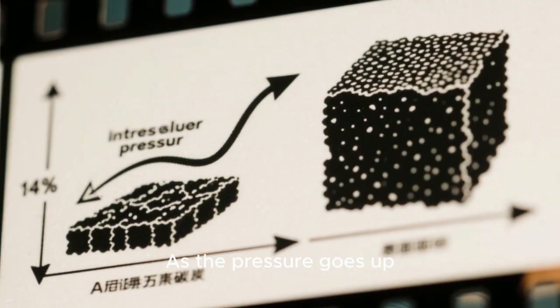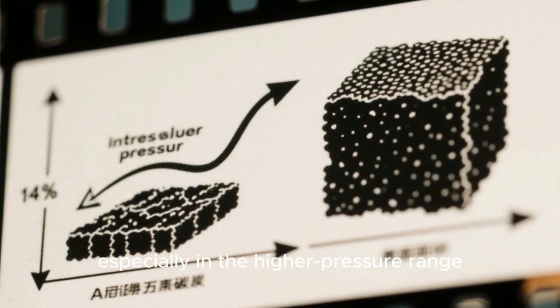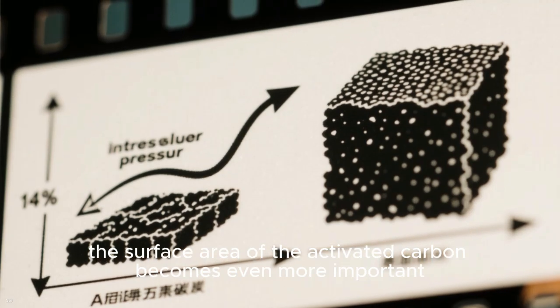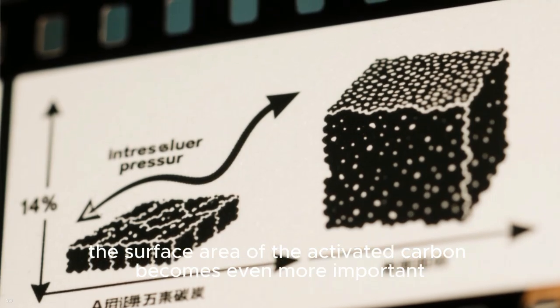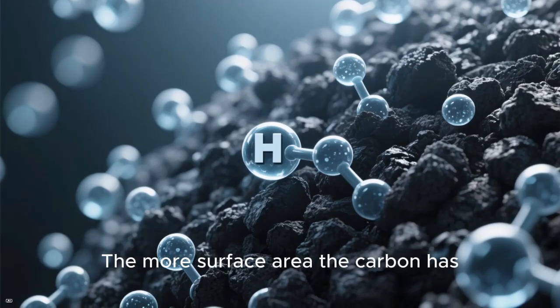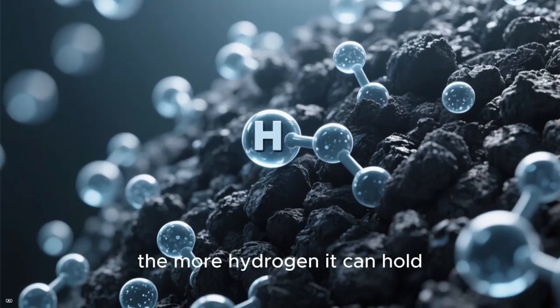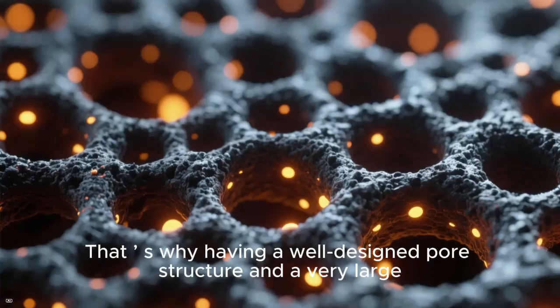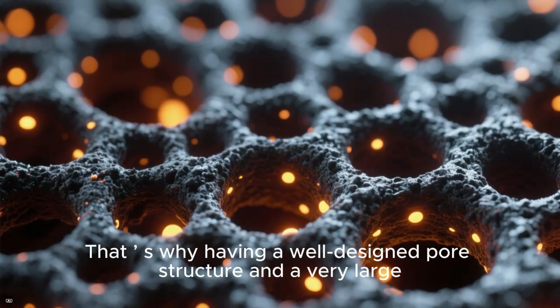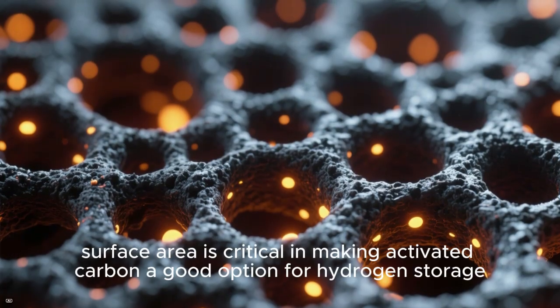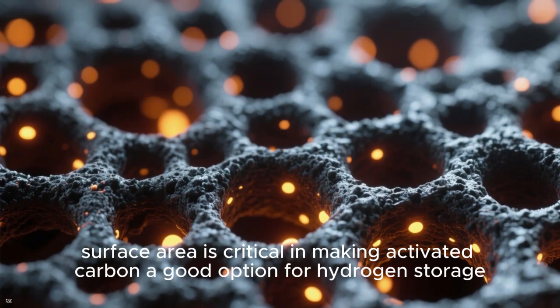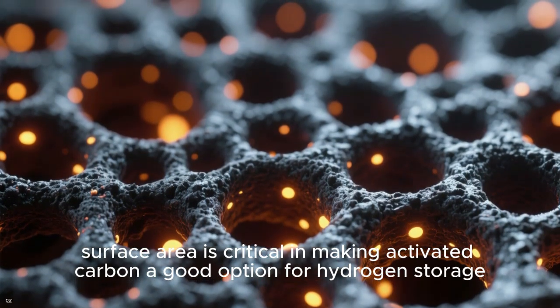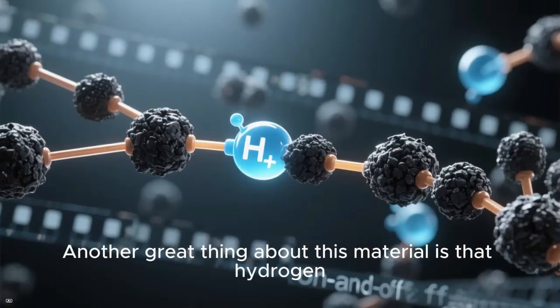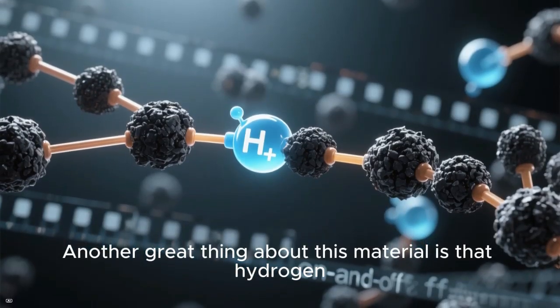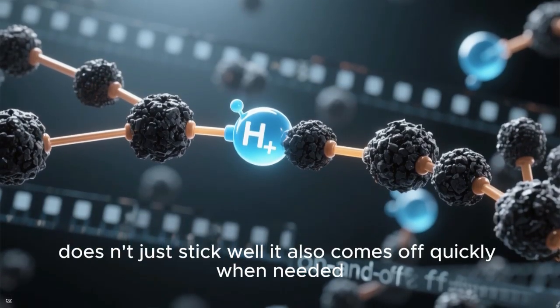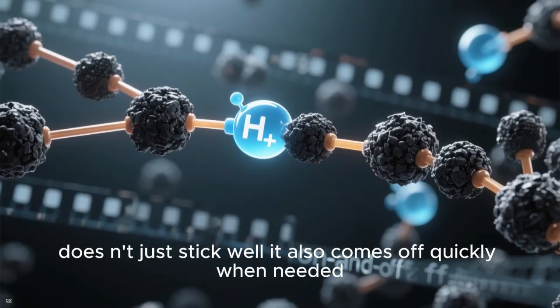As the pressure goes up, especially in the higher pressure range, the surface area of the activated carbon becomes even more important. The more surface area the carbon has, the more hydrogen it can hold. That is why having a well-designed pore structure and a very large surface area is critical in making activated carbon a good option for hydrogen storage. Another great thing about this material is that hydrogen doesn't just stick well, it also comes off quickly when needed.